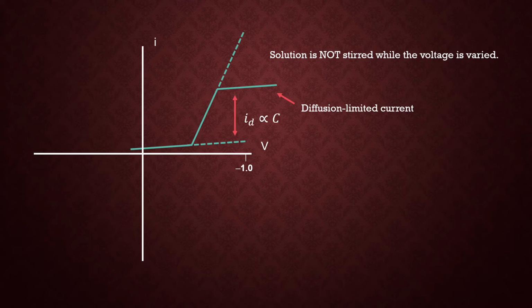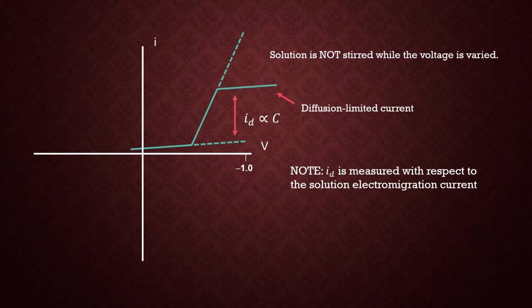So we call this I sub D, and it's proportional to the concentration in the bulk solution. We'll find out what the proportionality constants are in a bit, but this is the key point. The diffusion current at jump is proportional to the concentration of the unknown material in the solution. So also notice, and this is important when you solve problems or take tests, that you measure the diffusion current from the baseline indicated by that dotted line below. So in other words, the current voltage part, that linear section that corresponds to the standard conductivity of the electrolyte solution.